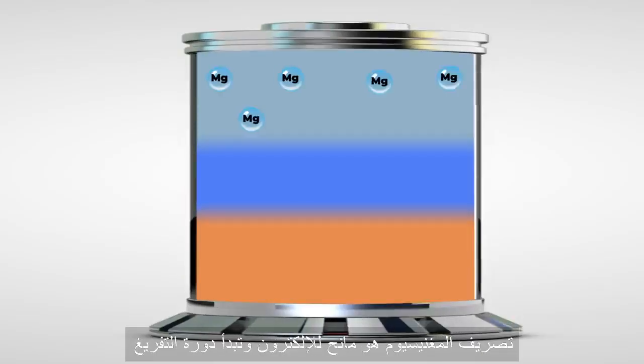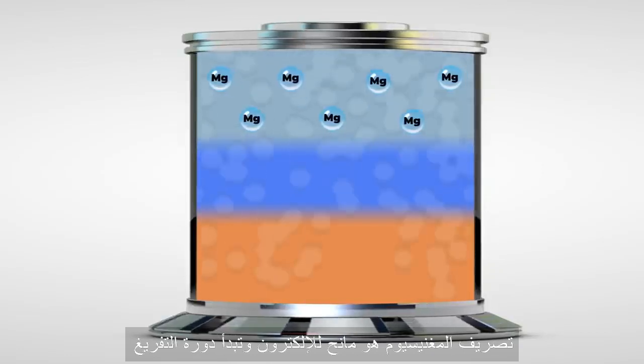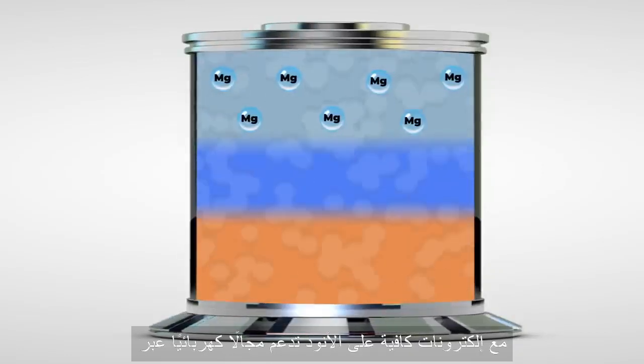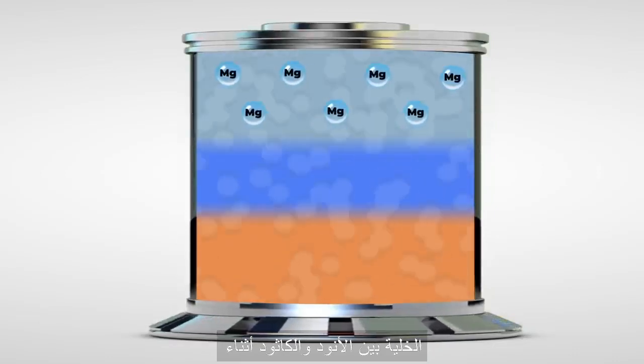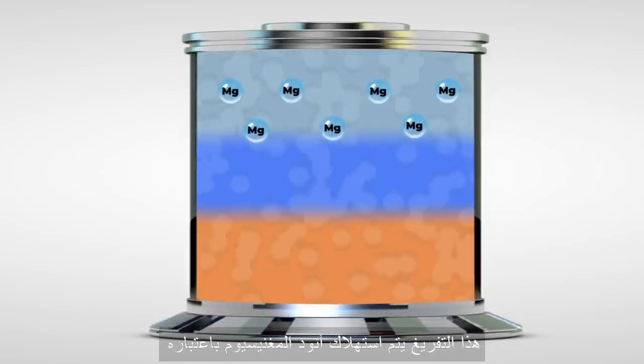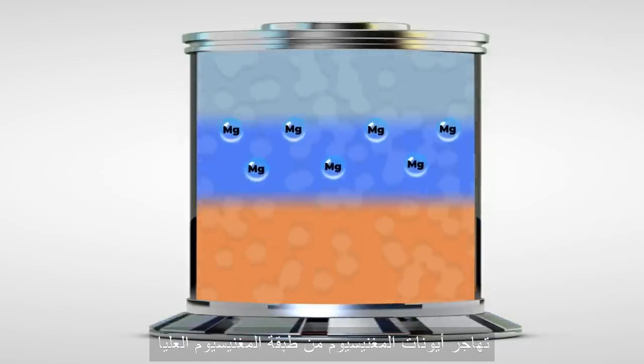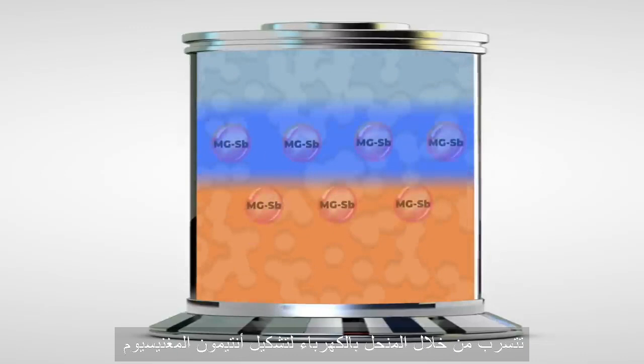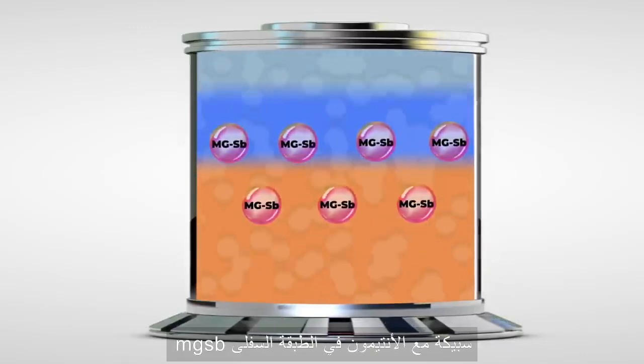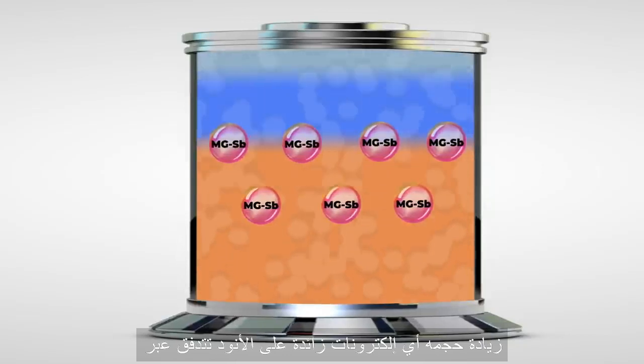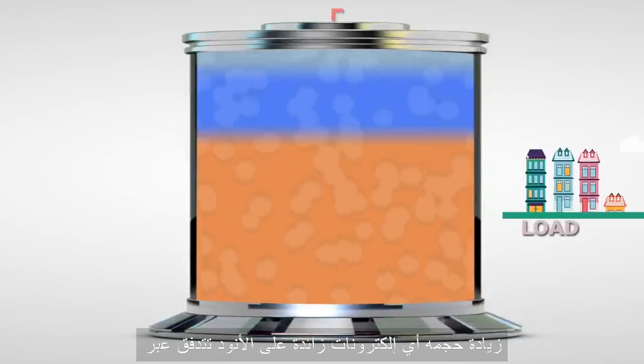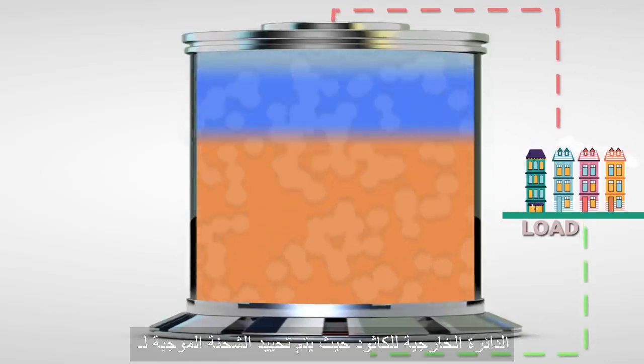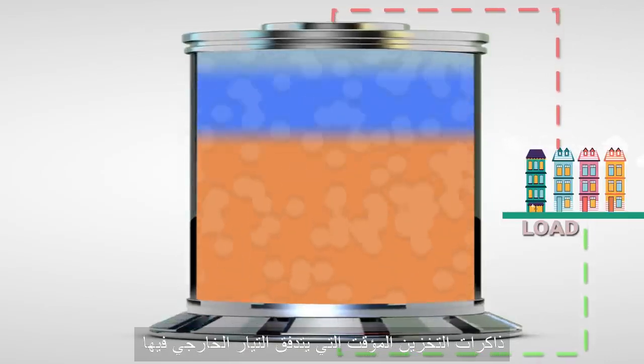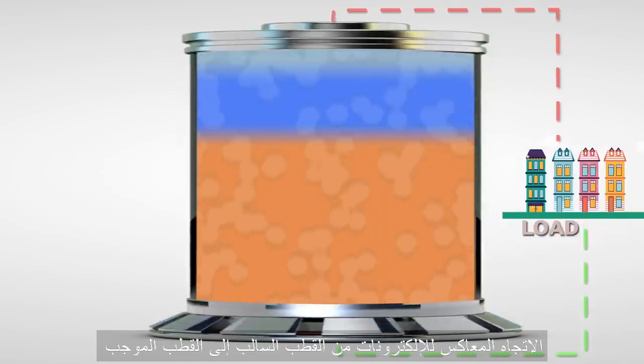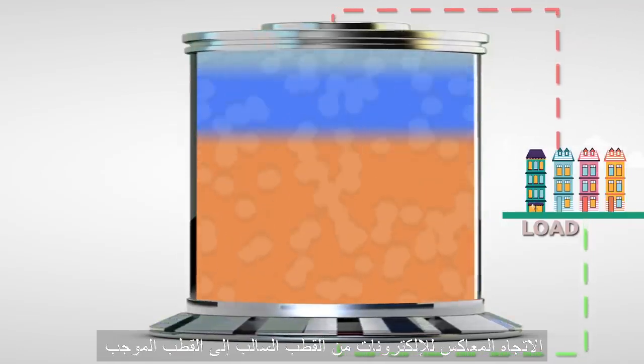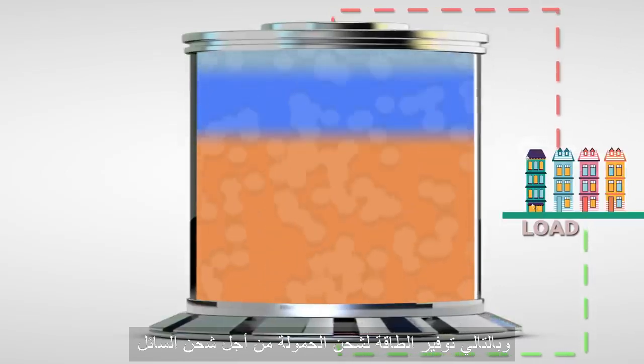Discharging. Magnesium is an electron donor, and the discharge cycle begins with enough electrons on the anode supporting an electric field across the cell between the anode and the cathode. During this discharge, the magnesium anode is consumed as the magnesium ions migrate from the upper magnesium layer, seeping through the electrolyte to form a magnesium-antimony (MgSb) alloy, with the antimony in the lower layer increasing its volume. Any excess electrons on the anode flow through the external circuit to the cathode, where they neutralize the positive charge of the cations. The external current flows in the opposite direction from the electrons, which is from the cathode to the anode, thereby delivering power to the load.